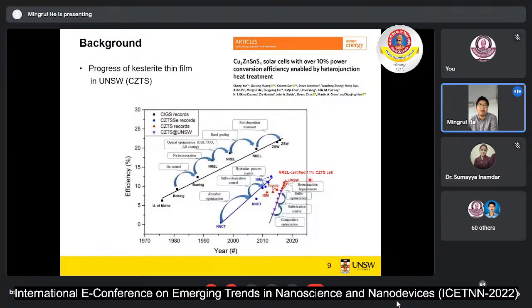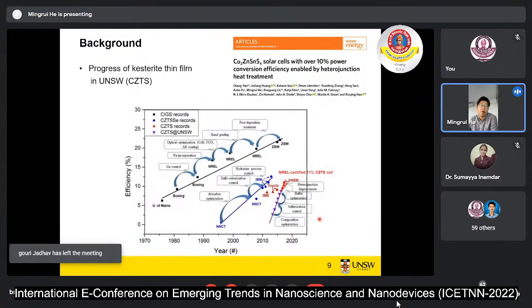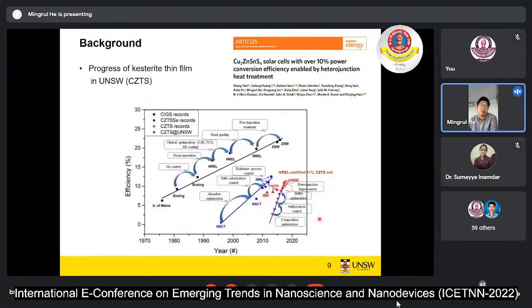It's certified 11% for the small area, 1 cm squared. For the larger area, it's around 10%. We published this article in Nature Energy. We continuously did different optimizations. Initially, we did the composition optimization, changing the ratio of copper to zinc, or copper to zinc plus tin. Second, we controlled the sulfurization, which is the formation of how we can form the CZTS materials.